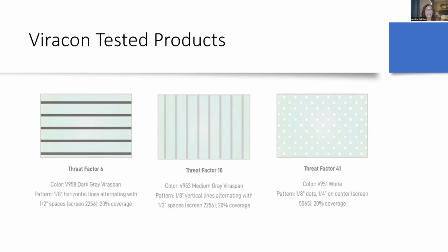The bird-friendly glass designs developed by Viracon have a screen printing pattern applied to the glass. The difference between them is the pattern and the color. Research indicates that patterns and colors help to reduce collisions regardless of whether the glass is insulated or laminated. Here are 3 of the Viracon printed products tested with ABC in the tunnel test. These are all silkscreen printed patterns, and colors used range from dark gray, medium gray to white.